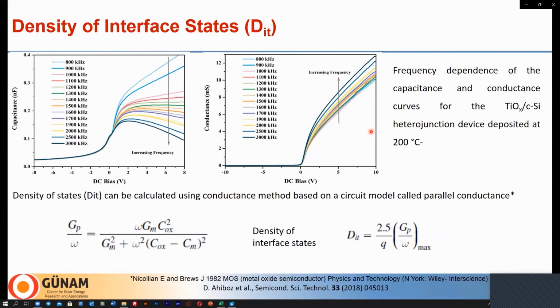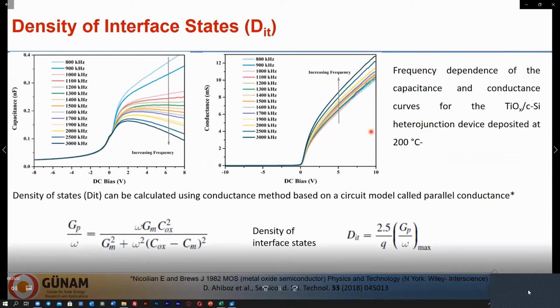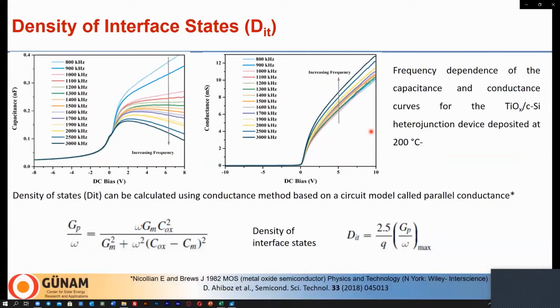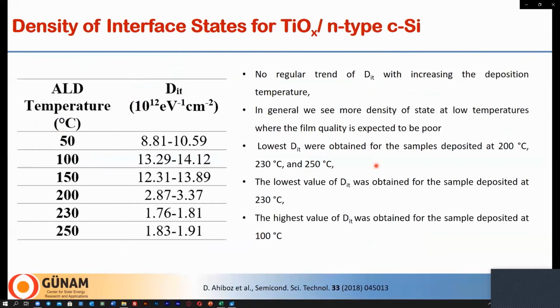This is a very well-known technique for the analysis of oxide structure. In this calculation method, you measure the conductance and convert it into parallel conductance. By using this model, you plot parallel conductance over frequency, and from that you can extract the density of state. This is the density of state that we extract from this analysis, and we have the values here.